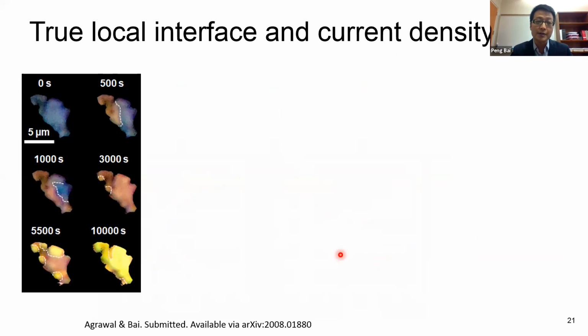So here, if you look at a single particle, you can see that from complete blue, you will nucleate some red phases, which is stage 2, and create this kind of phase boundary propagating through the particle. You can see that the phase boundary not only propagates, it evolves so that eventually the particle becomes totally red. Then after that, you will see this nucleation of gold phases creating new phase boundaries, right? Then eventually they sweep out the entire particle.